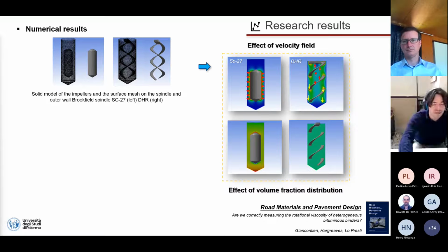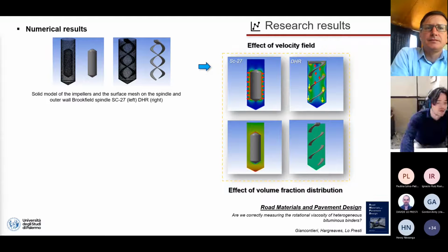The particle distribution investigation showed that using the standard spindle, the rubber tends to settle down to the bottom of the sample due to gravity, making the result non-representative. The DHR allows testing a well-distributed sample, and this theory contributes to guaranteeing the stable trend of results observed during the experimental campaign.